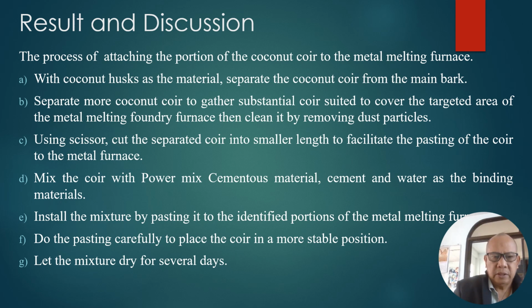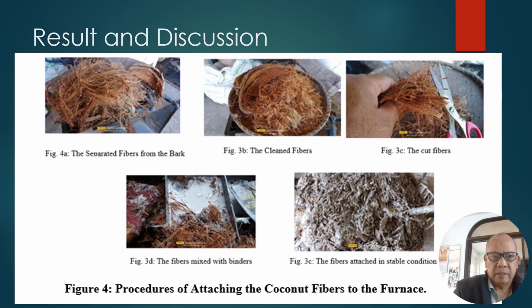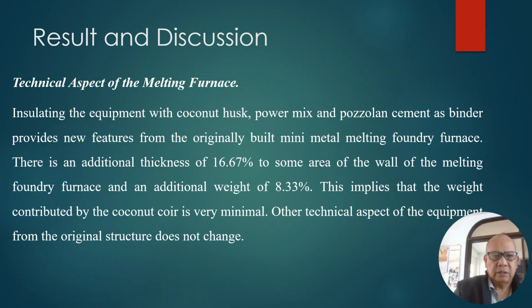Then I do the pasting carefully to place the coir in a more stable position. Then I let the mixture dry for several days. How the coconut coir was attached to the metal furnace is shown in figure 4, which shows the procedure of attaching the coconut fiber to the furnace. Then the technical aspect of the melting furnace: insulating the equipment with coconut husk, power mix, and pozzolan cement as binder provides new features to the originally built mini metal melting foundry furnace.